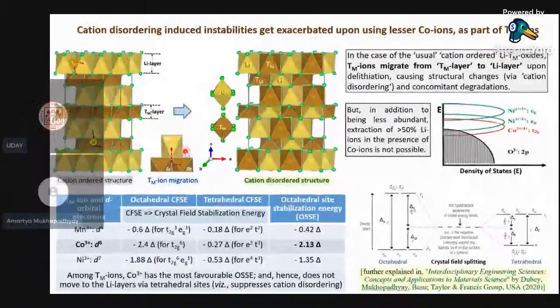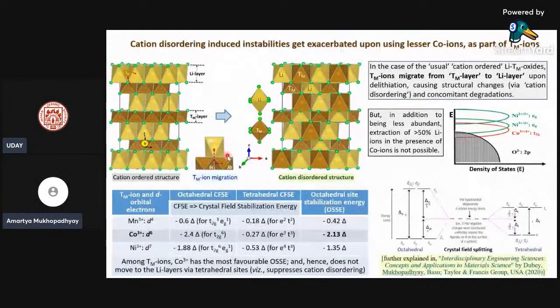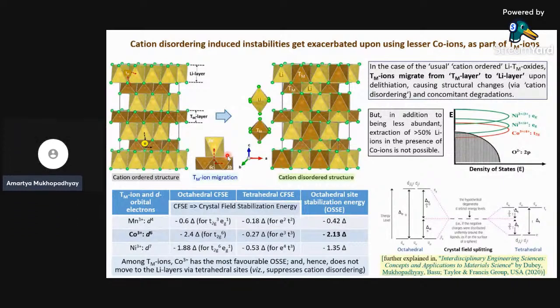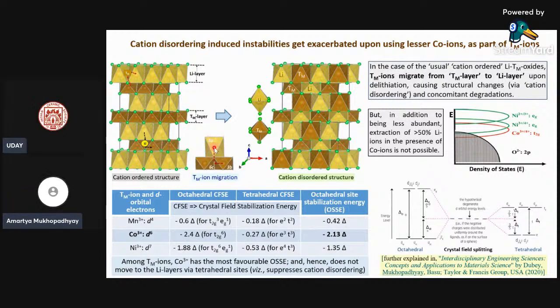So to preserve the structure while taking out more and more lithium, and that is going to high potentials, one needs to suppress this transition metal migration from the transition metal layer to the lithium layer, and that is very difficult to do.